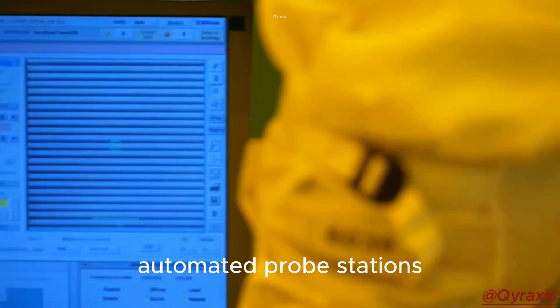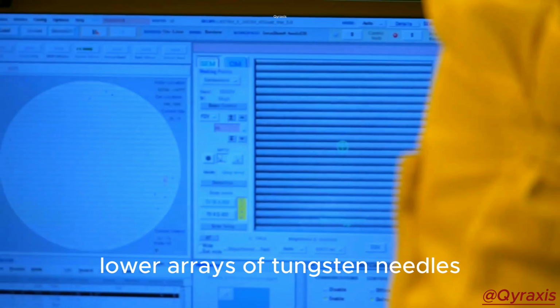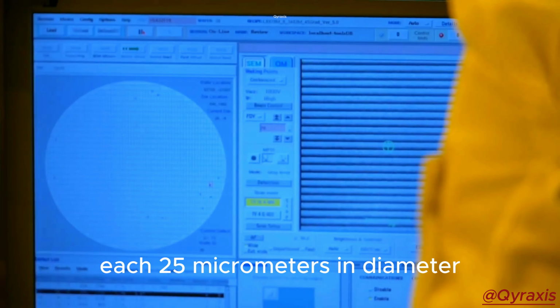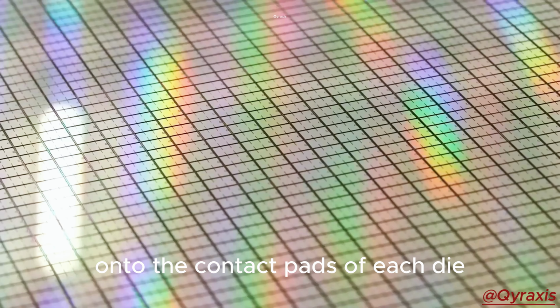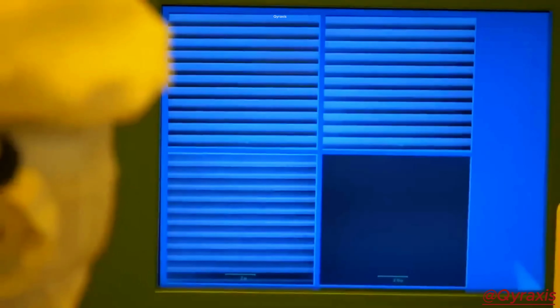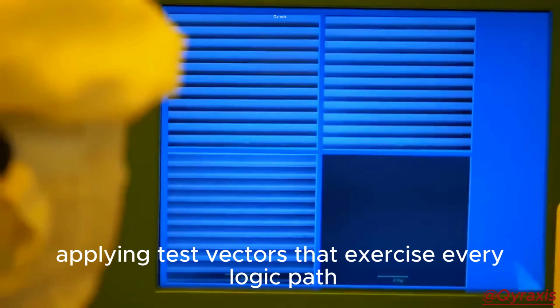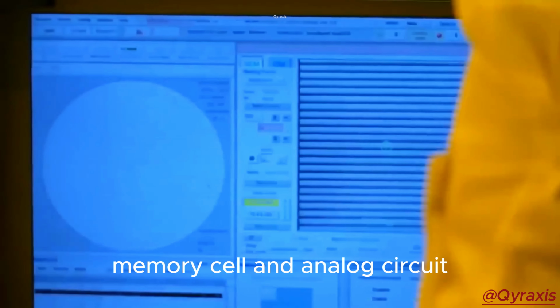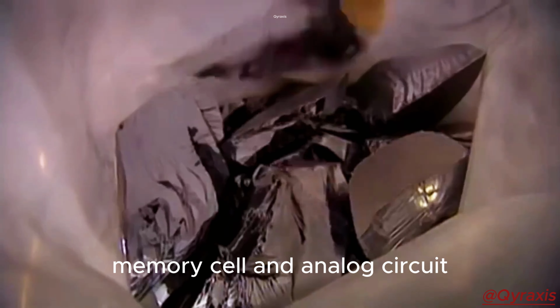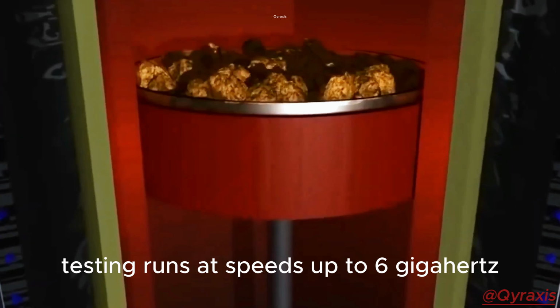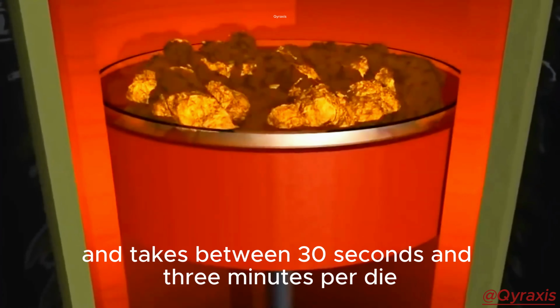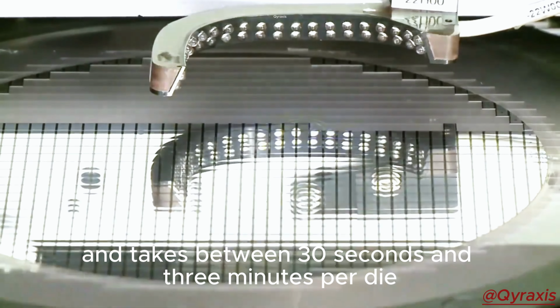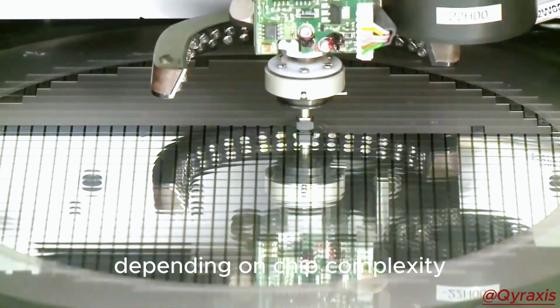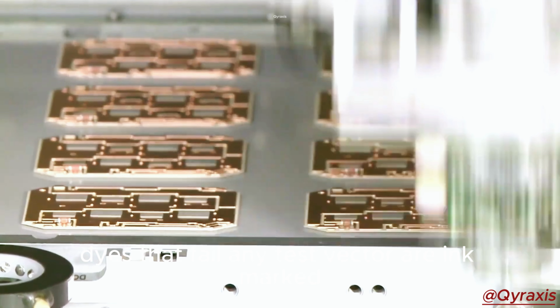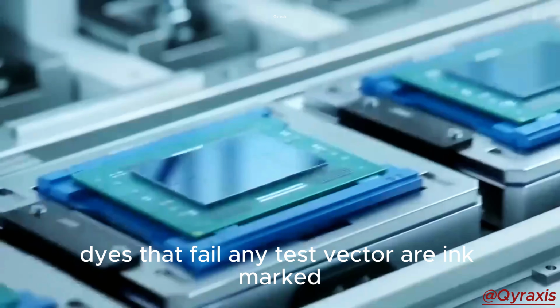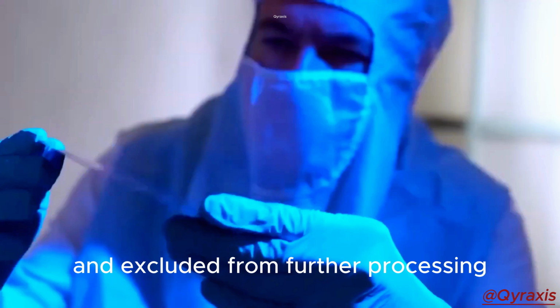Automated probe stations lower arrays of tungsten needles, each 25 micrometers in diameter, onto the contact pads of each die simultaneously, applying test vectors that exercise every logic path, memory cell, and analog circuit. Testing runs at speeds up to 6 GHz and takes between 30 seconds and 3 minutes per die, depending on chip complexity. Dies that fail any test vector are ink-marked and excluded from further processing.